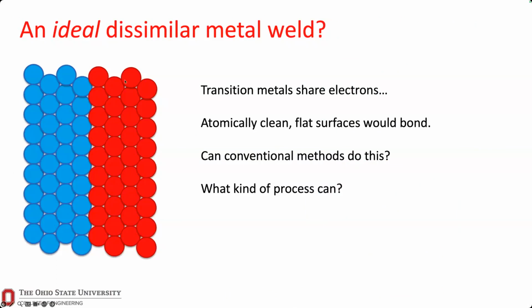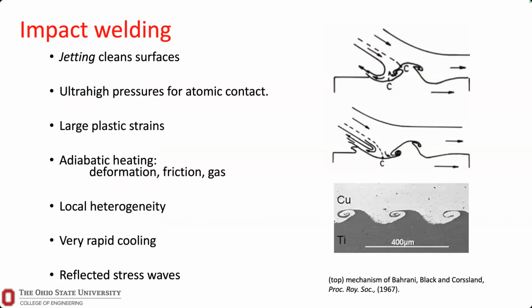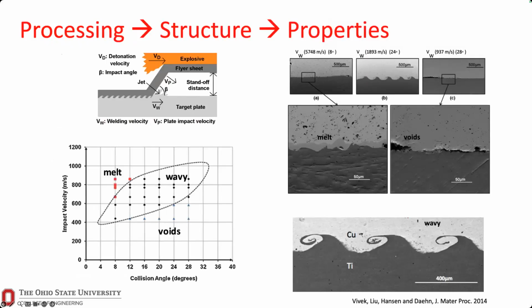The trick is, how do you keep any oxide from forming? How do you get these surfaces together in intimate contact without any oxide formation? How do you do that? Well, the way you can do that is by impact welding. This has been around for a long time, been used with explosive welding. And basically what happens is this top sheet comes in, collides at a very high speed, you're typically talking about on the order of a kilometer per second, very high speeds, you can form these welds. This is a weld that we formed in the laboratory between copper and titanium. What happens is that impact basically jets off the initial surface and allows intimate contact between almost arbitrary dissimilar metals.